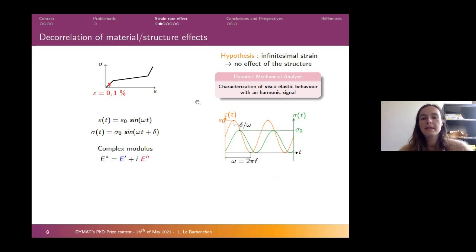Here we made a second hypothesis that if we solicit the material at infinitesimal strains, we will not have a structure effect. So if we study the material at sufficiently low strains, for example with dynamic mechanical analysis, we can characterize the mechanical behavior of the material without the structure effect.